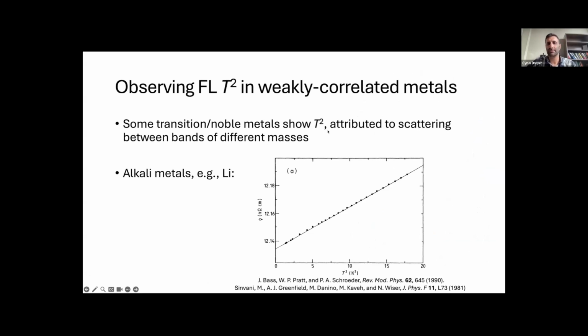There have been some normal metals where this Fermi-liquid T squared has been measured. Some transition or noble metals like palladium, I think, is the key example. They show T squared, but that has been attributed to scattering between bands of different masses, not the Umklapp Fermi-liquid scattering that we usually consider. Probably the most canonical examples are the alkali metals, where a very robust T squared has been measured at low temperatures, but there are still some questions in terms of the comparison between experiment and theory and the understanding of what's going on here. So I would argue that this Fermi-liquid regime in normal metals is really an unsolved problem experimentally, and therefore worth tackling theoretically.